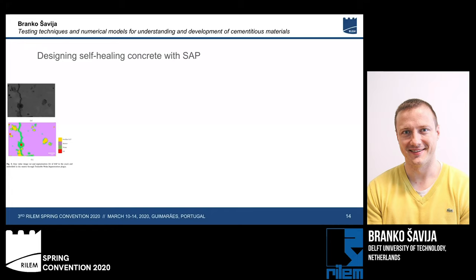And these materials have been used quite a lot in the field of self-healing materials, because as we see here, when a crack occurs, we will have an opening where water can penetrate and reach the SAP particle. This particle will swell and hopefully close the crack for water penetration, thereby increasing the resistance to transport and protecting our reinforcement, for example.